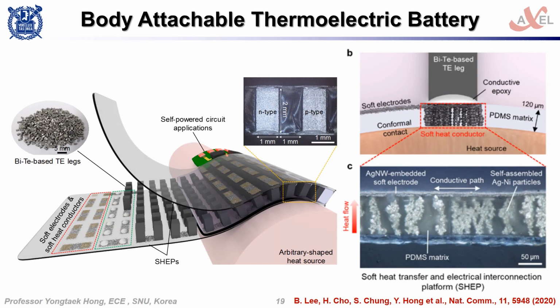Using SHEP technology, we recently demonstrated body-attachable thermoelectric battery technology. Using N and P-type rigid bismuth telluride legs, silver nanowire stretchable electrodes, and a soft heat-conducting structure, we developed a conformable thermoelectric array. In order to enhance heat conductance of the PDMS substrate, we embedded magnetically aligned silver-coated nickel particles in the substrate.